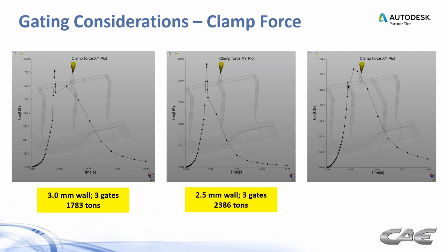Not only that, but you have to pay attention to what's going on with clamp force. So with those same 3 situations, we got the 3 millimeter wall with 3 gates, 1,700 tons. 2.5 millimeter wall with 3 gates, now we're up at 2,400 tons. So let's say you're slating this part to go into a 2,000 ton press. Well, now all of a sudden you reduce the wall thickness so much that you can't mold it in that 2,000 ton press. You have to go with a 2,500 ton press if you're going to stay with the 3 gate situation. But going to the 4 gates, we're able to get it back down to the 1,500, almost 1,600 tons. So clamp force is affected because the pressure is affected.